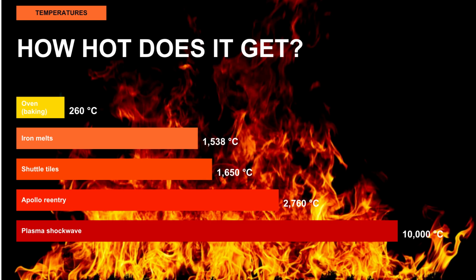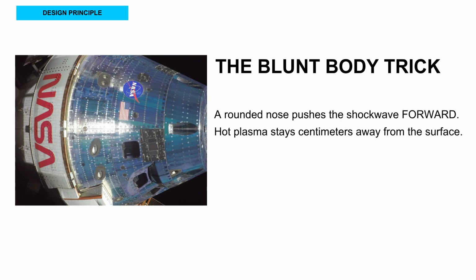The thermal protection system must keep the underlying structure, usually aluminum or carbon fiber composite, below about 177 degrees Celsius. That is a 1,500 degree temperature gap the material must bridge. The shape of the vehicle matters as much as the material. A blunt body, a rounded, wide nose, creates a detached bow shockwave. The hot plasma forms several centimeters in front of the surface, not on it. That gap is the first line of thermal defense.